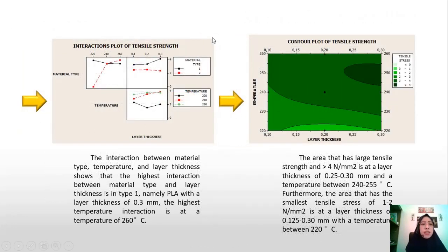And results and discussion. Next, the interaction plot between material type, temperature, and layer thickness shows that the highest interaction between material type and layer thickness is in type 1, namely PLA, with a layer thickness of 0.3 millimeter. The highest temperature is at 260 degrees Celsius. And after that, we can proceed with a contour plot of tensile strength.